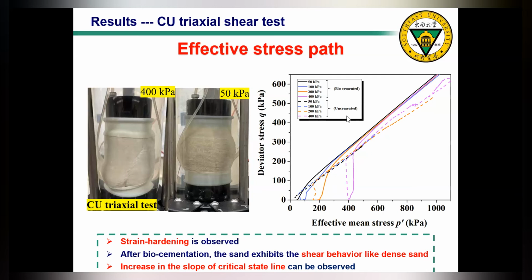Okay, then finally, if we look at the critical state line part, in some samples maybe the critical state is not fully reached, but in general, we can see that after biocementation treatment, the slope of the critical state line increases, and the critical state lines are at a higher location. The biocemented samples are higher than those of untreated samples.